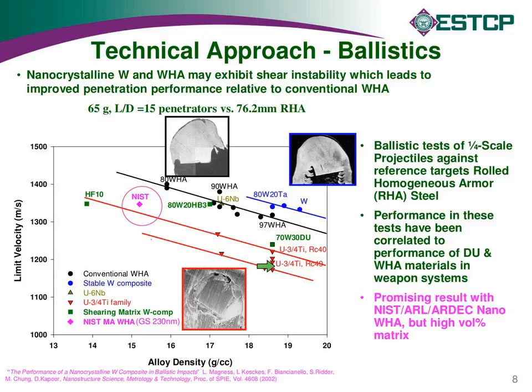Pure tungsten are these blue data points that are up here. If you look at pure tungsten or similar materials like tungsten tantalum, they're even more stable than the tungsten nickel iron materials. You see this extreme mushrooming behavior. So what you're seeing is it actually takes even more energy than a tungsten heavy alloy rod to get through the same target. The other thing I'd point out on here is we did have one early proof of principle with a nanocrystalline material that we did with ARDEC and with NIST, mechanically milling.